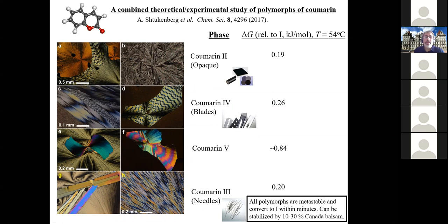Now, this last point is actually kind of an important one. It actually turns out most of these polymorphs are not very stable. They only survive for about a couple of minutes before they revert back to the stable coumarin 1 phase. But you can actually stabilize them long enough to get these images by adding the sap of the Canada balsam fir tree in there. So they actually add this Canada balsam into the structures, and then they will stay around for a few weeks.